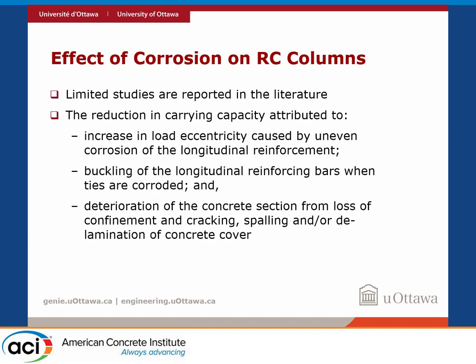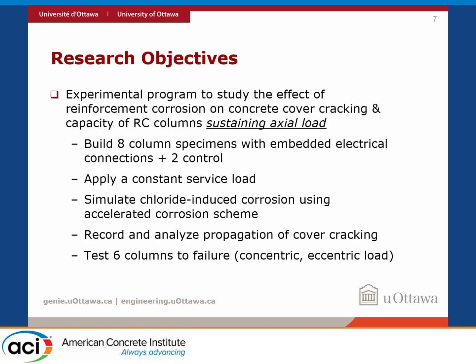We wanted to study the effect of reinforcement corrosion on cover cracking as well as the bearing capacity of short columns, but with a little bit of departure from previous studies, as we wanted to corrode our specimens while they were sustaining compressive load. So we built 10 columns. 8 of them were corroded, 2 were controls. We applied a constant service load through the process while they were being corroded.